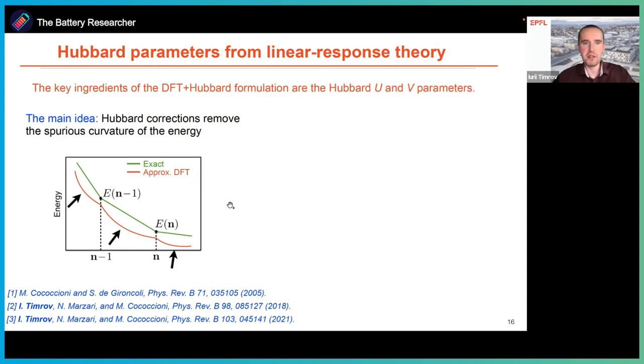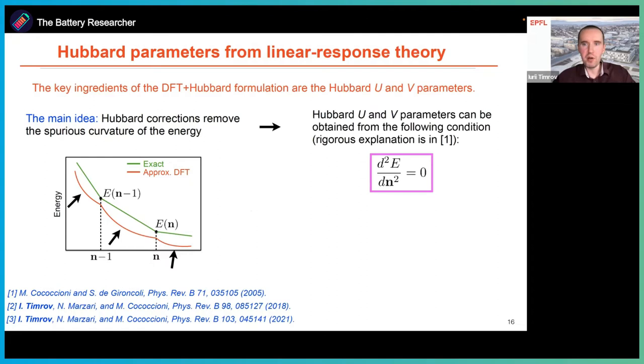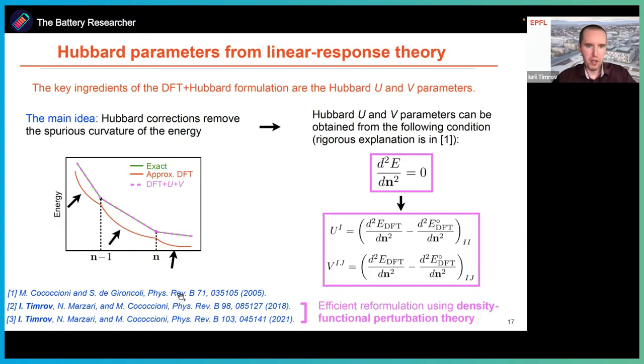So the idea is very simple. To determine these Hubbard parameters, we want to remove this spurious curvature of the total energy. With these arrows, I highlight the curvature and we want to get rid of it. So what we want, mathematically speaking, is that the second derivative of the total energy is zero. It was shown in the papers on the bottom left of my slide that from this condition, we can derive the precise and exact expressions for how Hubbard parameters can be computed. This is simply defined as the second derivative of the DFT total energy with respect to the occupations minus some non-interacting term. I don't want to go into the details.